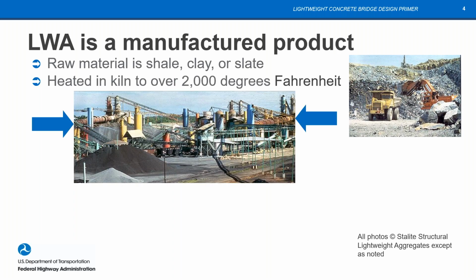So you use those as the raw materials, and then we heat them in a kiln. You can see the rotary kilns indicated by the arrows there. There are a couple of them at each side. Those kilns have the raw materials coming in from the top end, and it rolls down to the bottom. They're over 2,000 degrees Fahrenheit down at the low end where the flame is. So the material's getting heated up.